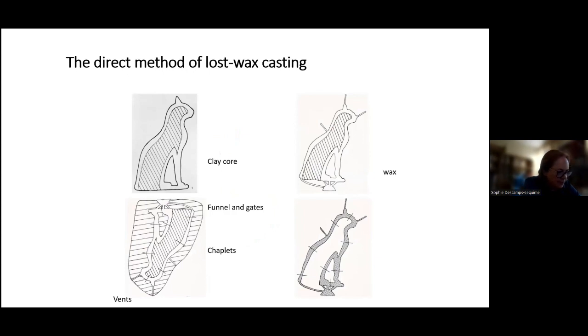When working on larger, necessarily hollow pieces, the craftsman first worked the clay, shaping the core. Here you can see it with oblique hatching. Then he added wax to the core to obtain the desired shape, without being able to control the thickness of the wax. Then the craftsman built in wax a network of gates connected to the funnel and vents for the evacuation of